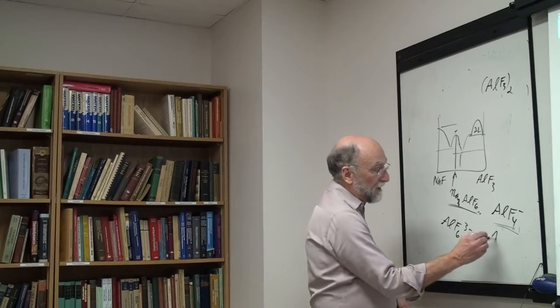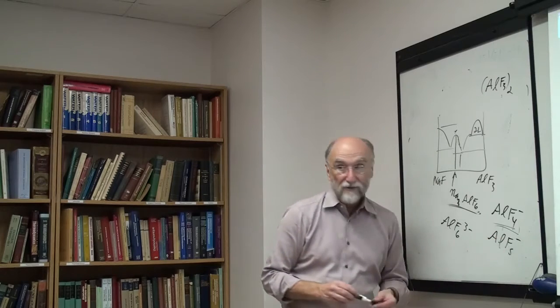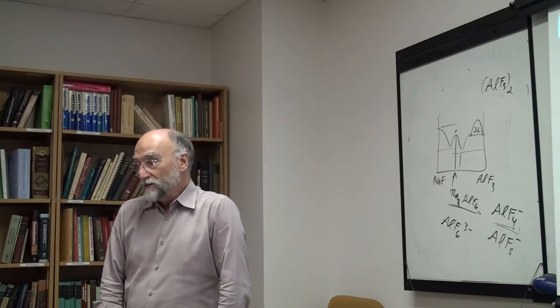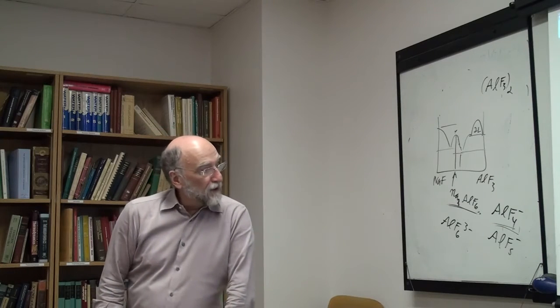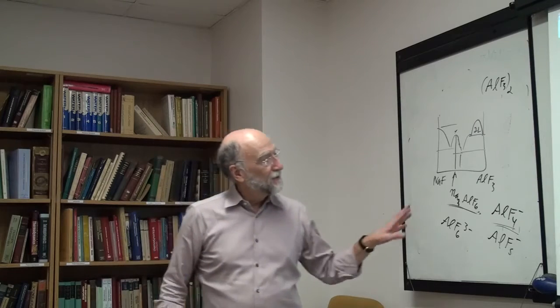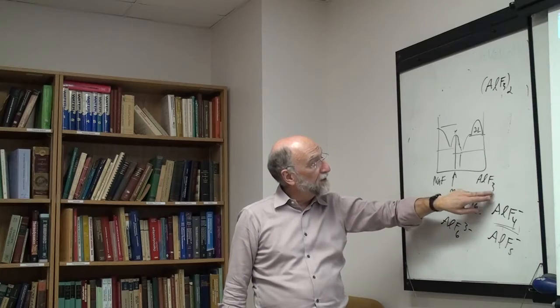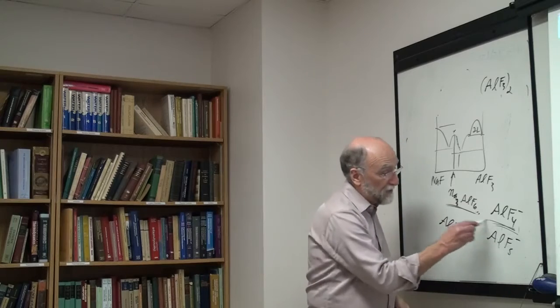In fact, to get a proper fit, Patrice has also added two complexes, AlF4 and AlF5, by a trick of talking about two kinds of aluminum, basically. There's tetrahedral aluminum and octahedral and pentahedral aluminum. And he gets a better fit considering two. He uses the quasi-chemical model with two different kinds of aluminum, but I won't go into the details. Okay, but the general point here is that when you're getting into the trivalent systems, the pure materials are not ionic, but they become ionic over on this side. And it does still seem to be the tetrahedral complexes that are important when you're dealing with trivalent stuff.